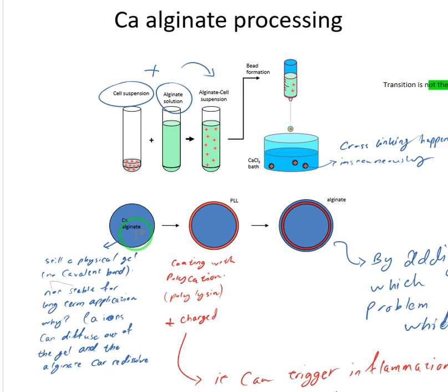So you see here when the gel is formed, the problem of losing the matrix is still present. If you remember, we mentioned before in the previous videos that some of the polymers of the gel can diffuse out, and when the concentration is decreased, we will revert back into the liquid phase. So we don't want that to happen. What we can do is to introduce on this negatively charged gel a positively charged layer of a polycation.